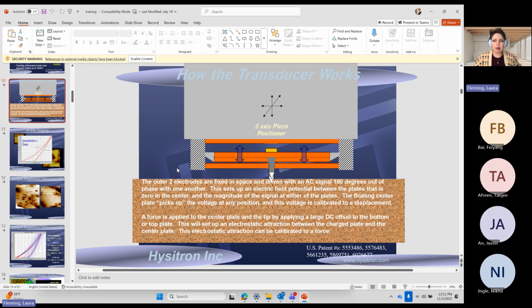So it works because the outer 2 electrodes are fixed. To measure displacement, we have an oscillating AC signal that's 180 degrees out of phase. As the plate moves through space, it works like an antenna, basically through an electric field. So as it moves, there is a relationship called our displacement scale factor between how far it moves and what that displacement actually means. So that's how that calculation is done.